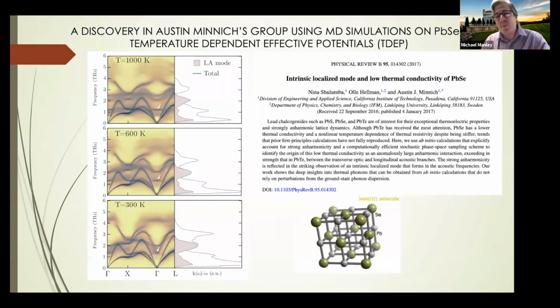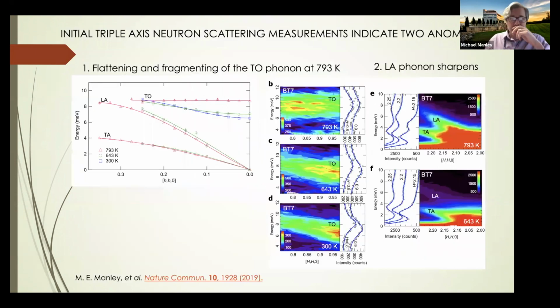This is very exciting to me because it's just coming out. They didn't try to make it. It just appears in the simulation. And since then, they've been seen in lots of simulations. You just had to get the simulations to work in this way, where they're very exact and include all of the anharmonic effects. So we got together and started doing experiments, and we can see that not everything is exactly as predicted, but there were certainly things that came together. For one thing, as we heated it up, if we look at this transverse optic phonon, so this is the transverse acoustic, longitudinal acoustic.